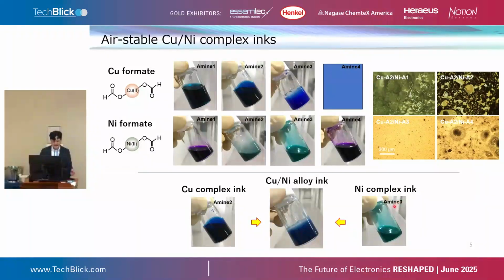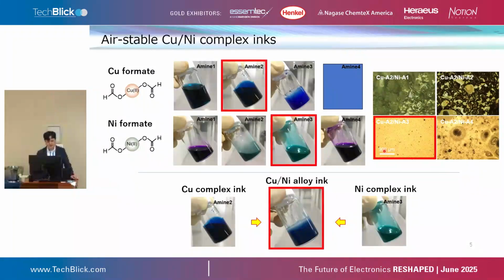And in this reduction process, the selection of the amine molecules is actually quite important. The difference in amine results in different surface morphology, as you can see in the right figures. We have checked a lot of different combinations of amine solutions. And finally, we found the best combination of amines for the copper and for the nickel formate. And now we have successfully synthesized the best copper nickel alloy.